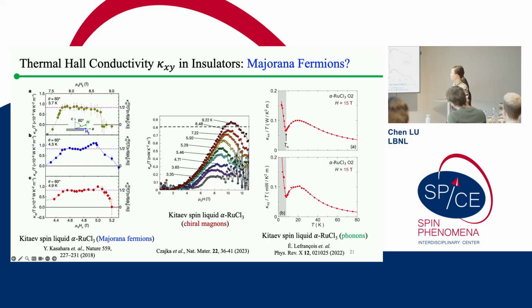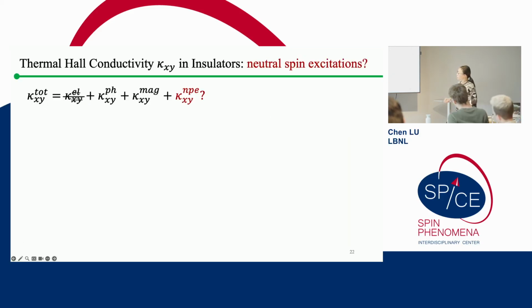And later on, our group at Sherbrooke also measured the same system. What I plotted here is thermal conductivity and thermal Hall conductivity versus temperature. If you compare these two curves, you will see their temperature dependence looks exactly the same. One thing about alpha ruthenium trichloride is that the thermal conductivity, we already know, is contributed by phonons, which are another neutral type of excitation. This indicates the thermal Hall conductivity probably has the same origin, which is also phonons.